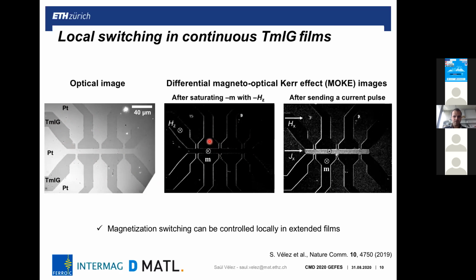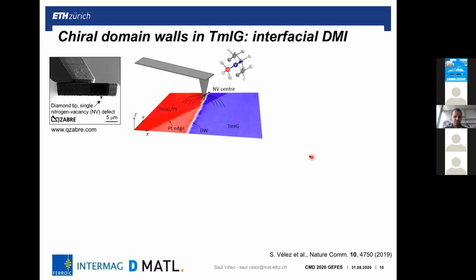We first saturate down the magnetization, then we send a current pulse, and we see that we switch the magnetization only in the current line, telling us that we can control locally the magnetization in continuous magnetic films, which could be interesting, for instance, for magnonic applications.